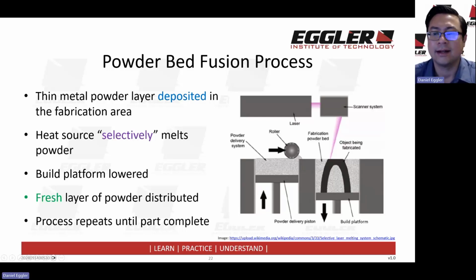Here it is conceptually. We have a powder chamber in the build volume. As you can see here, on the build platform, we initially have a powder layer. We have a laser that will selectively melt the powder and it creates what we call a melt pool. And this creates essentially the fused metal. Once we have our layer complete, the platform lowers, we get more powder, and then the process repeats itself. So, conceptually quite similar to what we typically do with powder bed fusion.